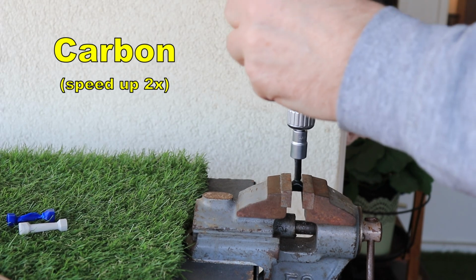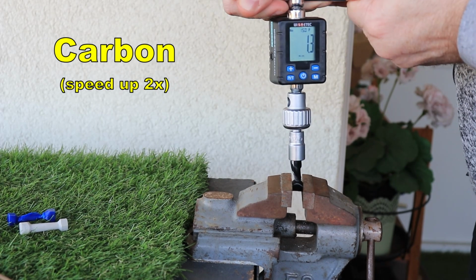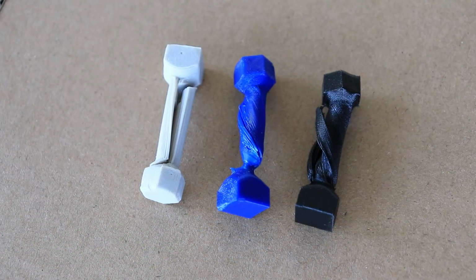1. 1.3 was the peak. Interesting, 3 different breaks. Surprisingly, the PETG was very brittle, but probably because of the weaker layer adhesion. For the deformation, the PCTG and carbon were similar, but they break on different load.